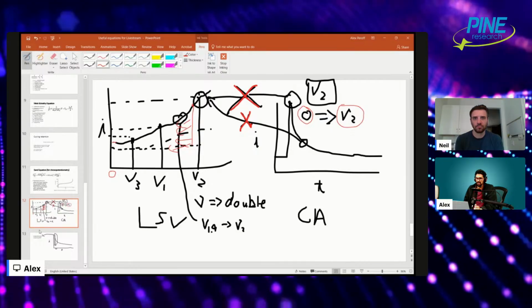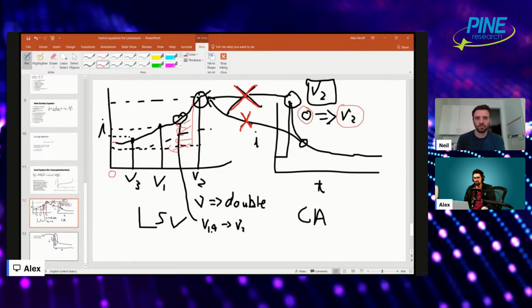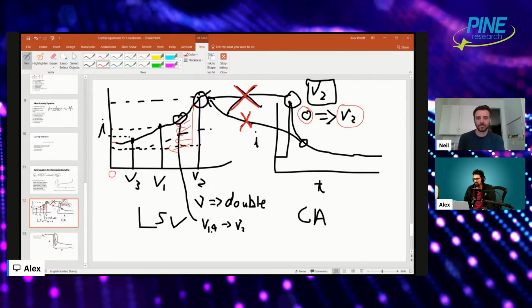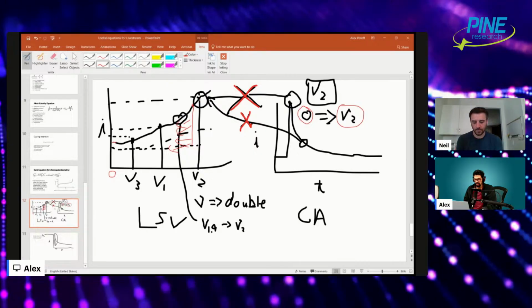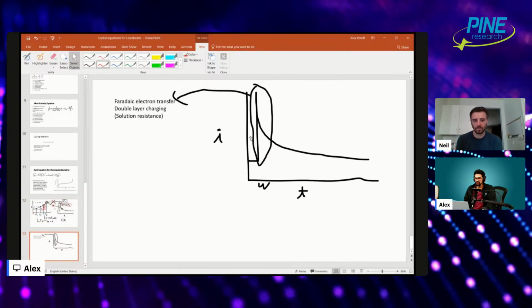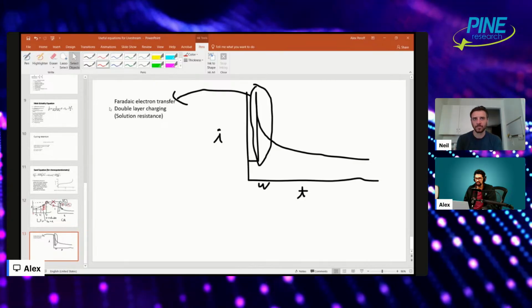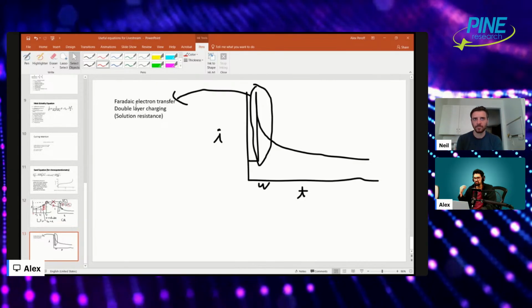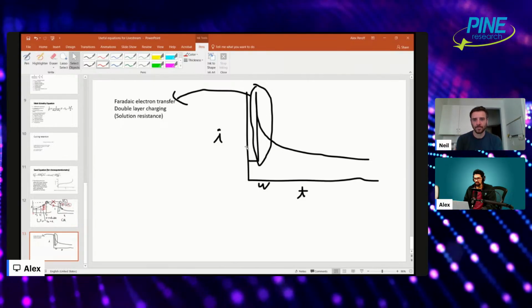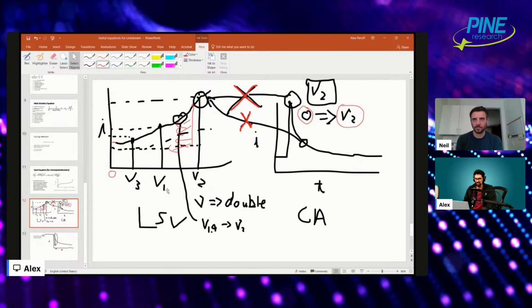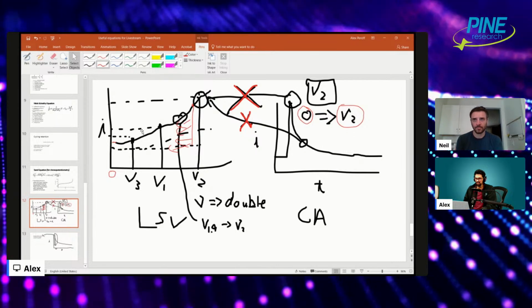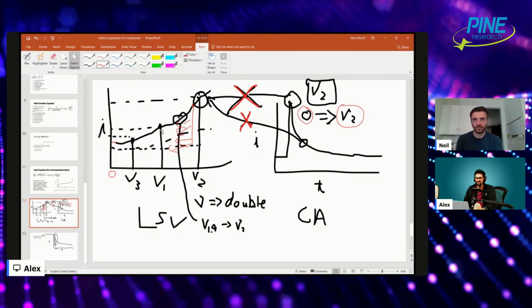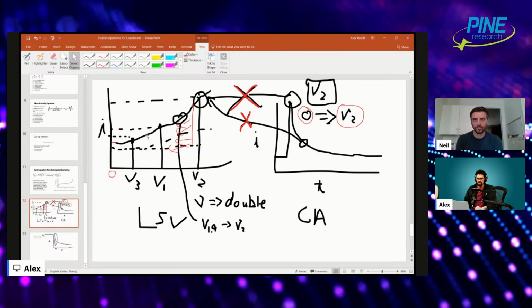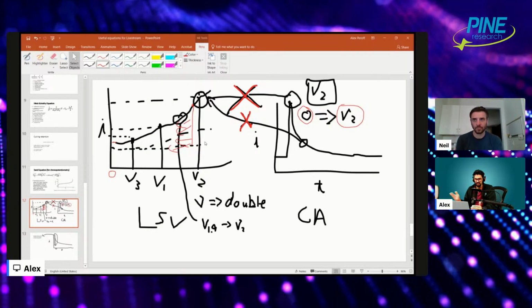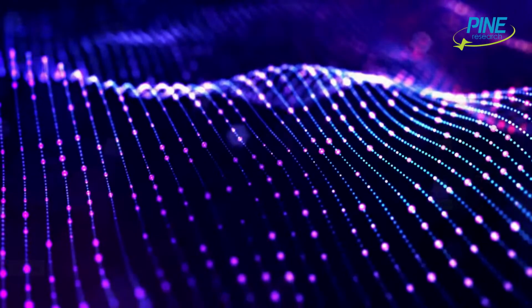So in my view, this is at least an explanation as to why the peak current here is not going to be equal to the current here. It's because the things that contribute to this current, the Faradaic electron transfer and double layer charging, are very different magnitudes in chronoamperometry versus LSV. A lot of the stuff that's happened at some of these potentials have already happened or have been accounted for at different potentials that are less positive or less negative, depending if you're doing a reduction or an oxidation. But that's the main thing. I hope that makes sense.